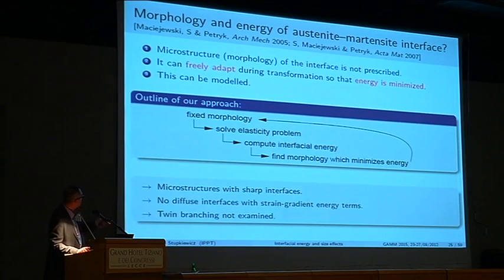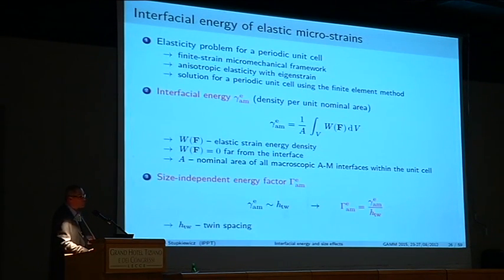So we apply the following approach. If we have a fixed morphology, we can solve a corresponding elasticity problem, we can compute the energy, and then we can try to improve the morphology or microstructure so that the energy is minimized. Okay? And in this approach, what we consider are the microstructures with sharp interfaces, so we do not consider any diffusive or gradient energy terms, and also, this is a little bit technical, we do not consider twin branching. So, yeah. Okay.